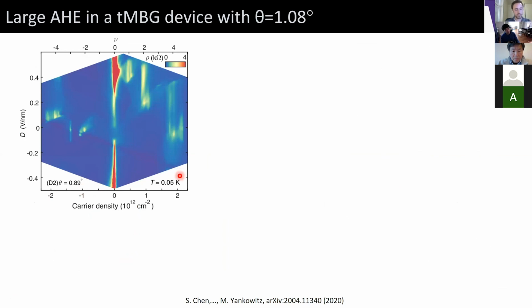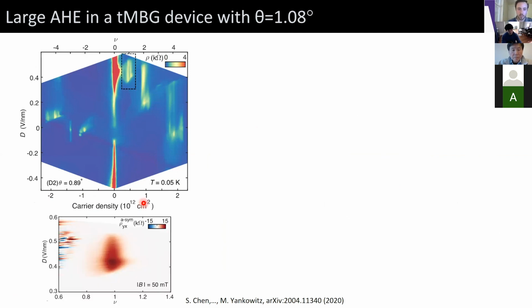Since I'm running low on time, I won't go into all the details, but the different thing is that on the twisted double bilayer graphene analogous side, we now have an additional correlated state at 1/4 filling of the band, which we did not have in the prior device. And if we measure the Hall coefficient, we see that it's actually very large, over 15 kilohm, in the region around this state at 1/4 filling of the band, and basically 0 elsewhere.